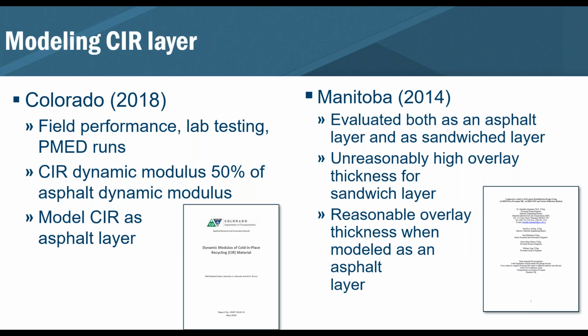One thing that we did find is how other agencies model the CIR layer. We were able to find information from both Colorado and Manitoba. Colorado actually did a study looking at field performance. They did a whole bunch of lab testing to quantify the CIR layer. They did a number of PMED runs. Pretty much found out in laboratory testing that the CIR is about half the stiffness of the asphalt dynamic modulus. And they actually suggest that you model CIR as an asphalt layer. Manitoba went through the same process.